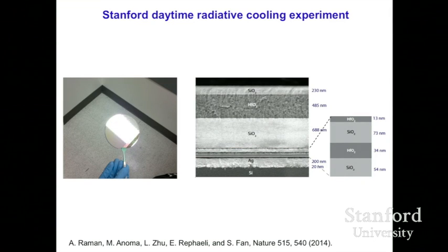Daytime cooling, on the other hand, requires a more sophisticated structure. And so using a numerical optimization, we have further simplified this design. And the result is now just a multi-layer structure. It consists of 7 dielectric layers made of silicon dioxide and hafnium oxide sitting on a silver mirror that was deposited on a silicon substrate. The top 3 layers here have a thickness on the order of hundreds of nanometers, and these are primarily for emission purposes. The lower layers here have a thickness on the order of tens of nanometers. These, together with the silver underneath here, produce a mirror that has very strong reflectivity.